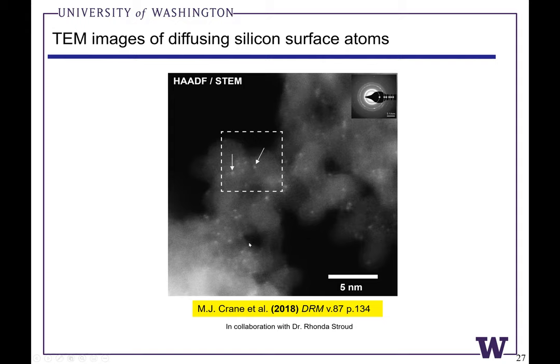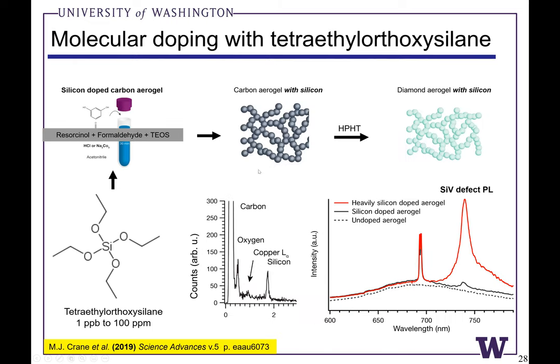And we're scratching our heads wondering, what's causing this? Why should we have silicon? And most likely it's vacuum pump oil, we think, in the lab. If you have high surface area materials, it's like a sponge, and any modest vapor pressure of, say, silicone grease in a Schlenk line from a vacuum tube could deposit on the aerogels, and effectively the aerogels will trap these materials. So these are diamonds that we made without any silicon, and there's no silicon split vacancy emission, but we can actually see silicon atoms from the pump oil adsorbing onto the surface. So with that knowledge, we were confident that at least for surface coating of the carbon materials, silicon is everywhere in a lab at PPT levels, from vacuum pump oil or PDMS, there are a lot of laboratory sources.